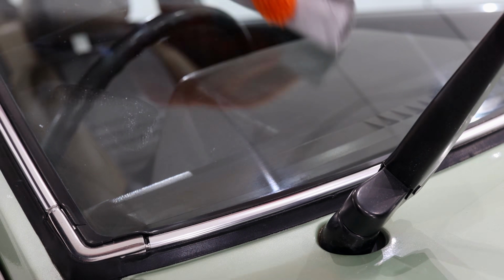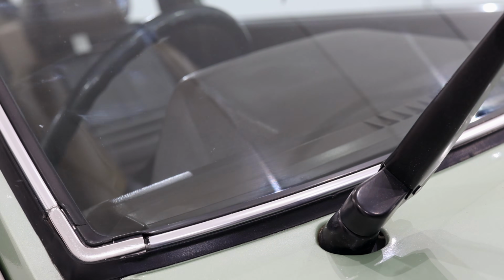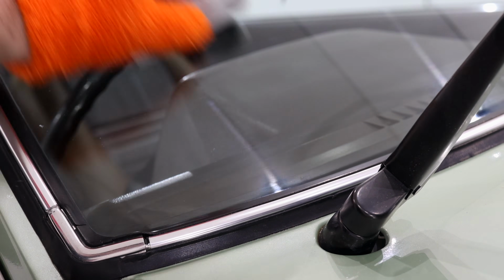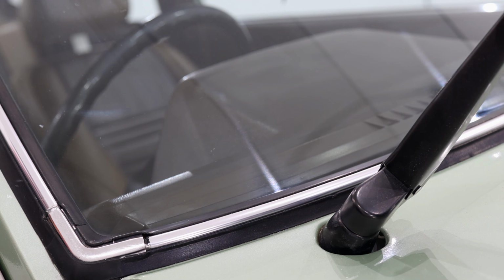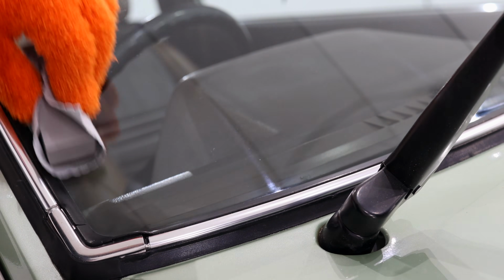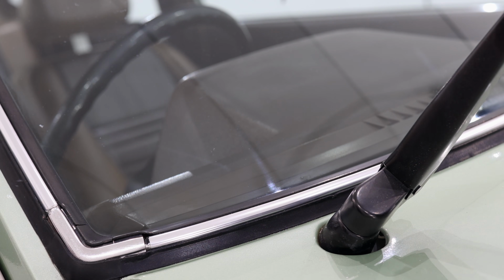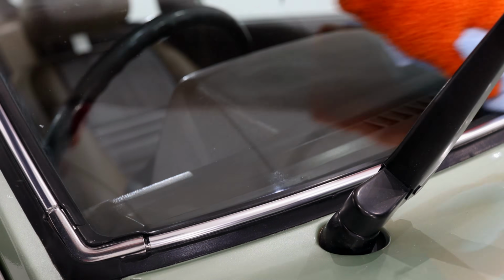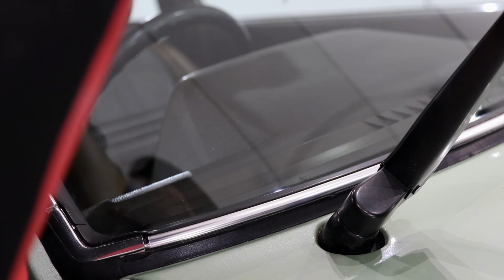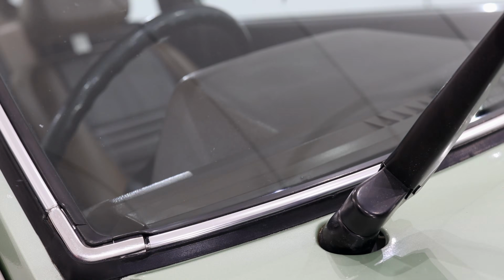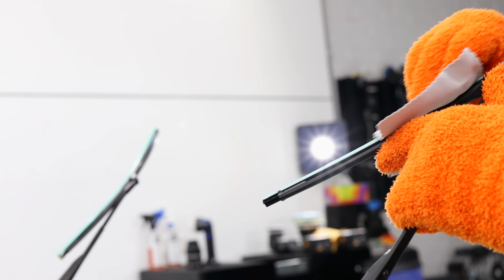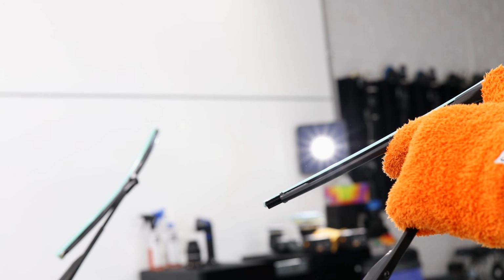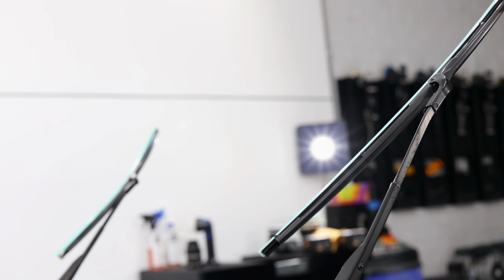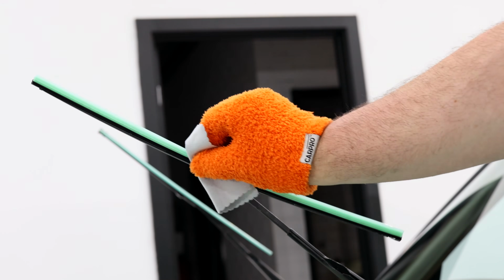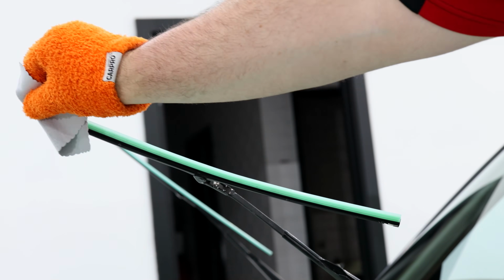Apart from that, try to keep the wipers off the glass or rolling the windows up and down for at least 6 hours. But within about 12 hours, the coating should be cured enough to use the car as normal, and within a couple of days, it should be fully cured. The added benefit of a high-performing glass coating is that at normal driving speeds in the wet, you may not even need to use your wipers, as its extremely hydrophobic nature should propel the water droplets right off. And in most cases, if you've done a good job at preparing and applying a quality glass coating, it should last at least a good year or 2.